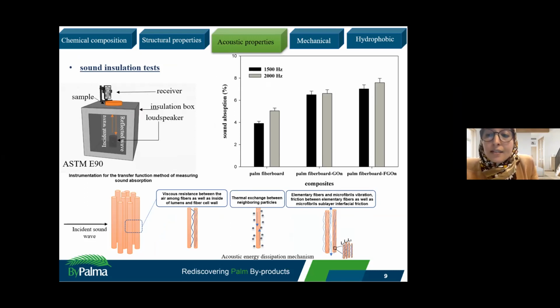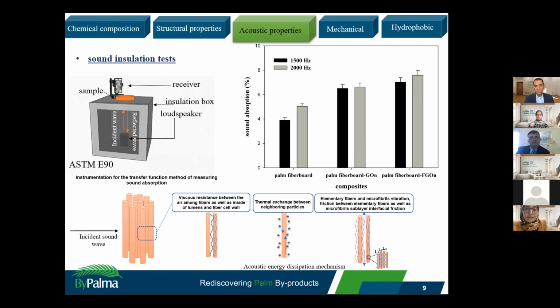So as you see, the mechanism illustrated in this figure shows that there are 3 phenomena that may enhance the acoustic properties of our fiberboard panels, which include a viscous resistance between the air among fiber as well as inside of lumen and fiber cell wall, the thermal exchange between neighboring particles, and finally elementary fiber and microfibril vibration friction between elementary fiber as well as microfibril sublayer interfacial friction.